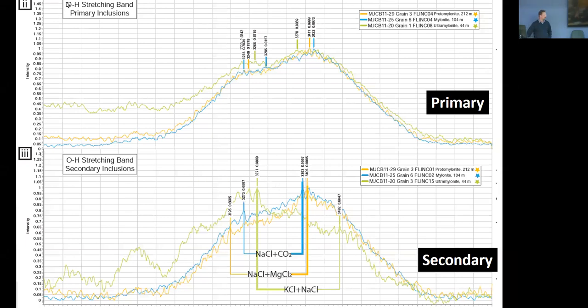Based on these OH stretches, the bands that are developing from that, they have concluded that there are different fluids that have been in different, should I say, times or different fluid inclusions in these samples that they had. And this is very low noise type of information. And again, it's just one way of looking at these fluid inclusions. This is not going to tell you that this was definitely a combination of sodium chloride and magnesium chloride, but it's an indicator that these are there, and it can guide additional analyses.